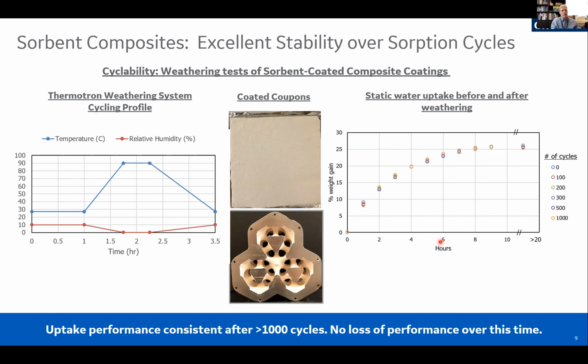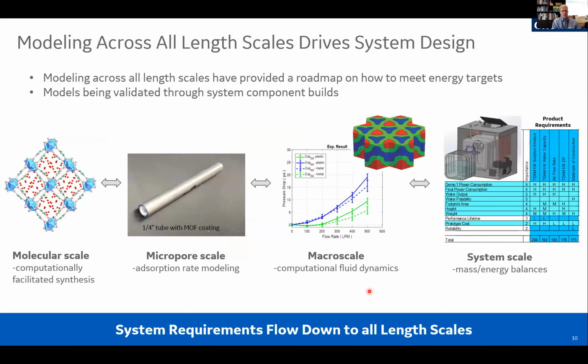Here is just an example of how we can coat these coupons, beautiful coated coupons with the MOF 303 plus our binder system. We can get systems that you can see right here. We can coat these and then test these over thousands of cycles. And we see no degradation of this material with not just the MOF 303, but also with our binder systems on the composite structures. So modeling across all length scales is extremely important, because this is what allows us to understand how the system works, and maybe more importantly, how the system does not work, so that we can optimize not just the energetics, but also the system design and process.